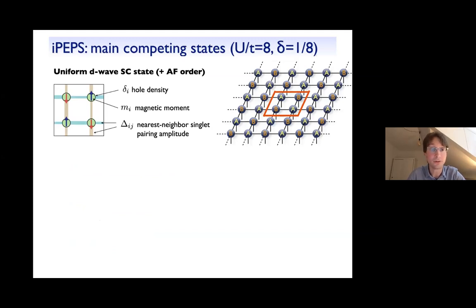Okay, so let me show you now the iPEPS results for the 2D Hubbard model. So these competing states that we obtain by using different unit cell sizes. If you use a unit cell just with 2 tensors A and B, we reproduce the uniform d-wave superconducting state, with coexisting antiferromagnetic order. What you see here, these green disks scale with the local hole density. You see here it's uniform, and then the arrows show you the antiferromagnetic order. And finally, these bonds scale with the local singlet pairing amplitude on the bonds, with different signs in x and y directions, which is what we expect for a d-wave pairing.